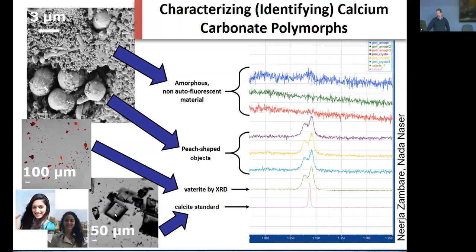So what we did then is we took an optical calcite standard and acquired a spectrum. You can see it's right between these two peaks, and a sample that we had identified as vaterite using XRD. And what you can see here is it really looks like these materials are, at least on the surface that we can probe with this, mostly made of vaterite. We have not been able to find any vaterite spectra in a reference database. So we don't know that, but that's what I said earlier. Sometimes you compare it to standards that you have characterized to the best of your abilities.